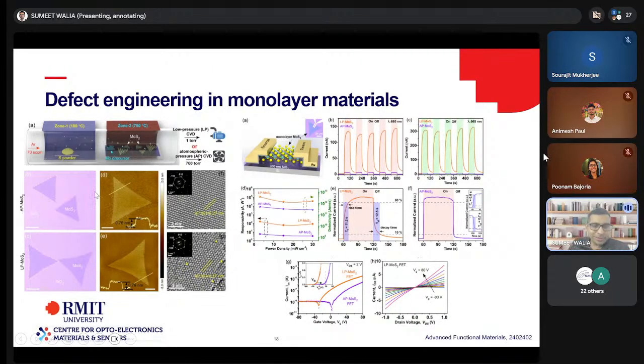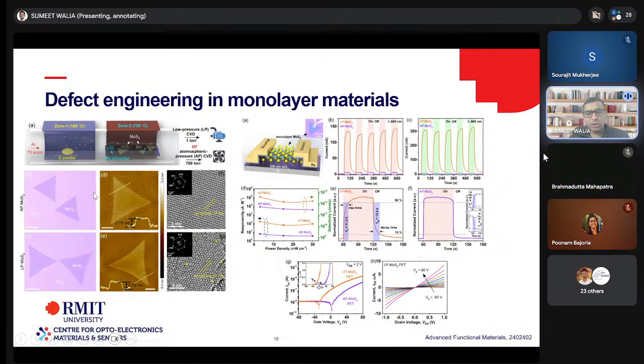And what we compare is, by slightly tweaking the amount of oxygen in the system, we are able to actually quite significantly change its electrical and optical properties. So if you look at the field effect transistor example down the bottom, when there are more sulfur vacancies, you have a negative threshold shift, because sulfur vacancies introduce negative charges, so you expect that to have an n-type doping effect.